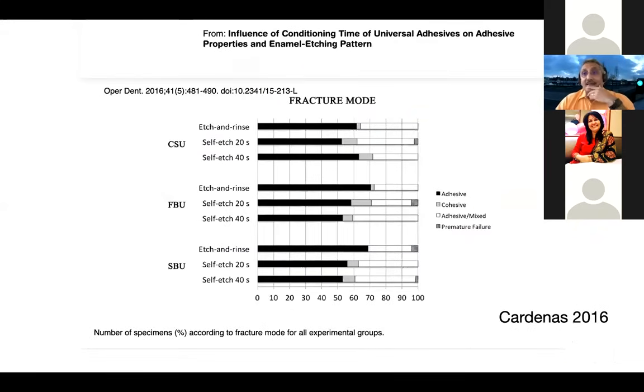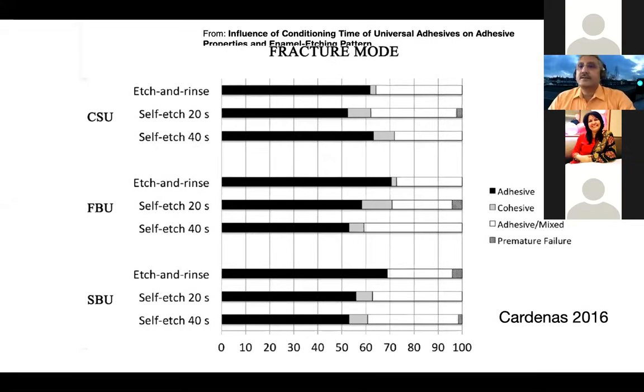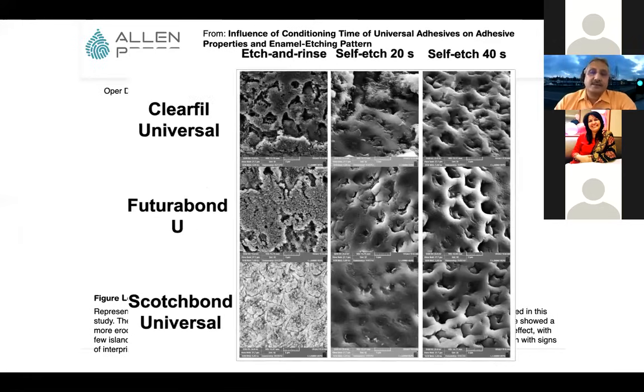Now, are there any things which you can do? There is this beautiful study, and there are other studies also which have corroborated that. What if you did self-etch for longer than the manufacturers recommended? Most manufacturers recommend, say, 20 seconds. Here, Clearfil Universal and Scotchbond Universal are both recommended for 20 seconds. What they did in this study was increase the self-etch time to 40 seconds. So now they have three groups here. In one group, they've used etch and rinse. The second group, they've used self-etch for 20 seconds as the manufacturer recommended. The third group, they've used self-etch for 40 seconds. And surprisingly, what you find is that if you increase the self-etch time to 40 seconds, you get a much better etching pattern on the enamel.